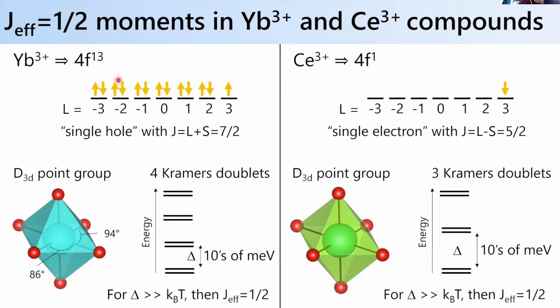And so the same argument applies when you go from ytterbium 3+ to cerium 3+, okay, which is a 4f1 system, and which again, with Hund's rules, gives me a J 5/2 state. And again, I put it in a D3D point group, which is relevant for the triangular lattice compounds I'm talking about. And again, you have, in this case, only 3 Kramers doublets. But again, the exchange interaction is much weaker. So when you're measuring low temperature properties, it should typically act as a good J effective 1/2 ion. Okay, so that was just some single ion background.